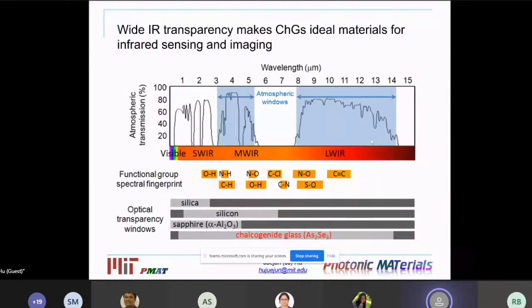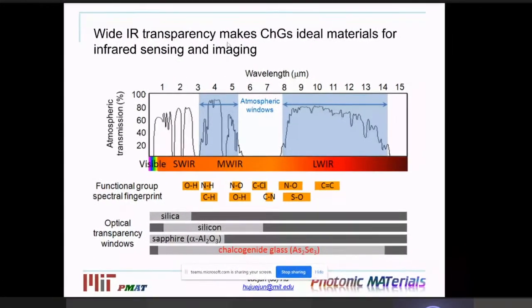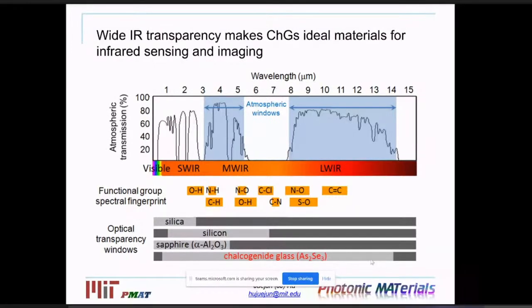Now, quantitatively, we can take a look at this spectra here. On top, I'm showing a wavelength scale, and at the bottom here, I use this gray bar to represent the transparency window in different materials. You see that silica is getting cut off at around 3 microns, but chalcogenides enjoy a very wide transparency window all the way from the visible to the long wave infrared. And this also overlays with many absorption fingerprints of different chemical molecules. And that's why these chalcogenide glasses are actually ideal material candidates to create on-chip photonic sensors.